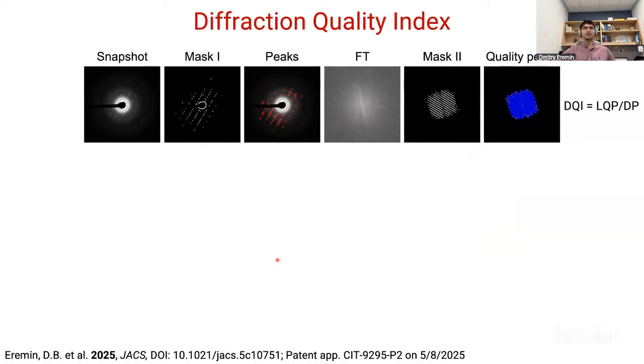So the logic, the actual math behind Reyes, is as follows, and we introduce it as the diffraction quality index. For every single diffraction pattern we collect, we create a binary mask that filters out all the background and noise and tries to fish out only the diffraction peaks. Then we count those diffraction peaks to the best of our ability, completely excluding the very center to make sure that we're collecting information about the high resolution frame. Then we do the fast Fourier transform of this binary mask, and we repeat the process. We find the peaks coming directly from this Fourier transform, and we count them.